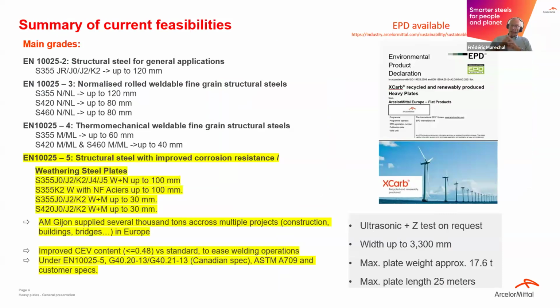So the mill in Gijón produced the major grades for construction, such as the well-known family of S355. We can do it in normalized treatments up to 120 millimeter thickness. We also do the more difficult, more demanding grade of S460N also, in this case up to thicknesses of 80 millimeter. And we also do these kind of grades in thermomechanical treatment.